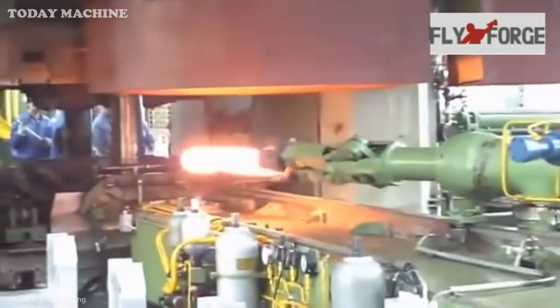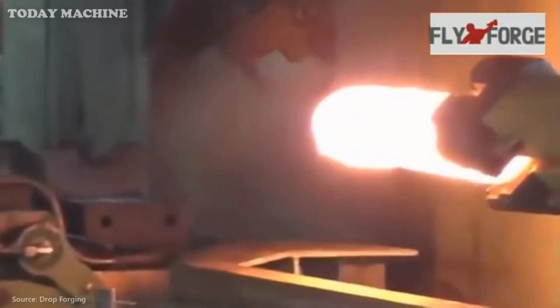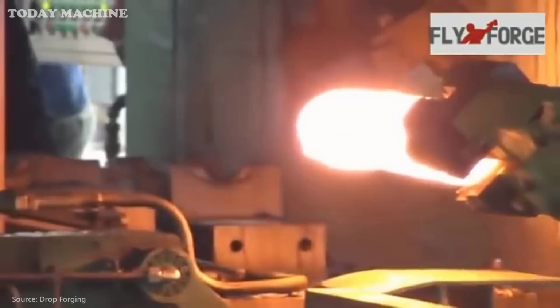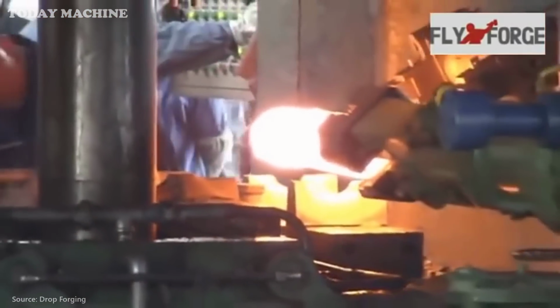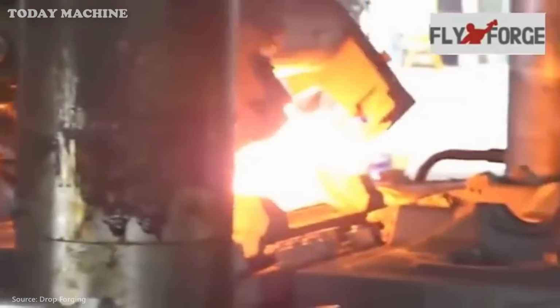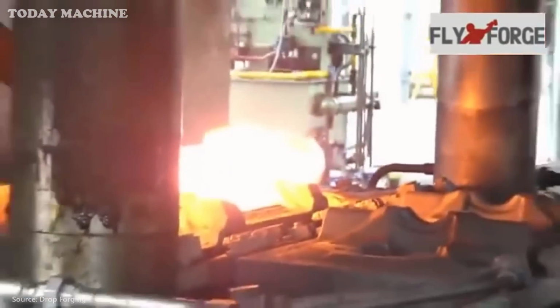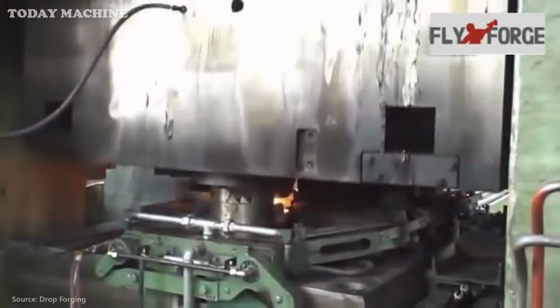Due to the deep decarburization layer in domestic raw materials, peeling is essential to remove this layer and enhance the surface quality of the crankshaft. The blanks are heated in a stepwise gas furnace to a forging temperature of 1180 degrees Celsius. Uniform heating ensures optimal plasticity and prevents internal defects.